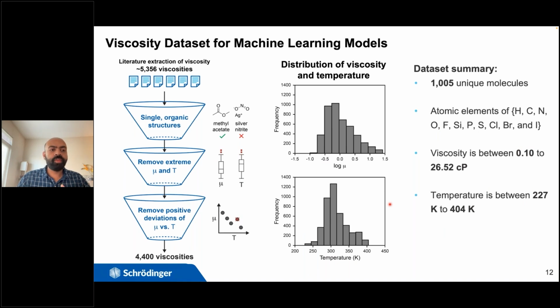Similarly, moving on from polymers, I would like to give an example of how we can use a combination of MD, molecular dynamics, and machine learning to improve the prediction of properties of molecules as well. So here is a case study where we performed machine learning for viscosity, and we carefully extracted more than 4,400 viscosities from the literature. We searched through the entire literature and looked at handbooks, looked at publications, and we filtered out molecules that were not appropriate for machine learning, if they were charged or if they were mixtures, and we removed values which had extreme values of temperature and viscosity.